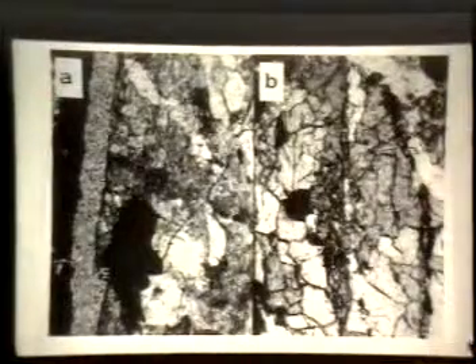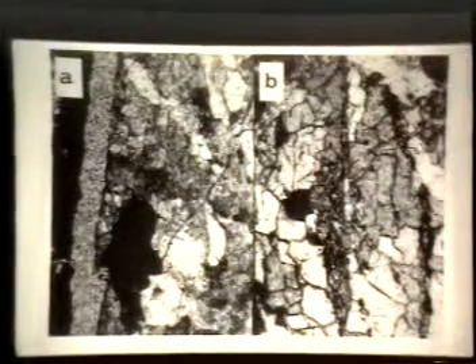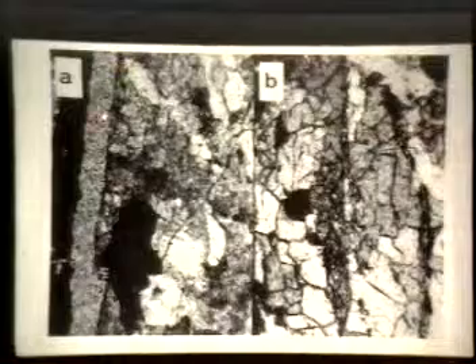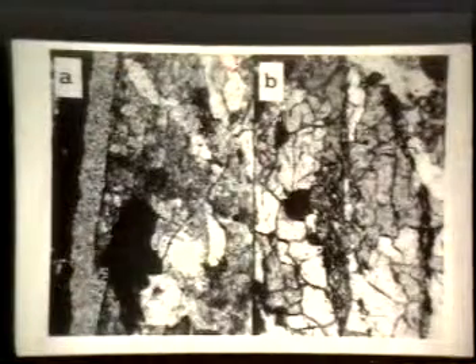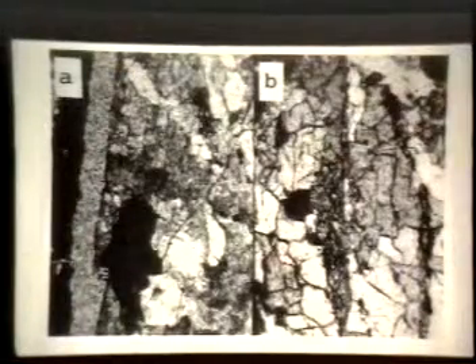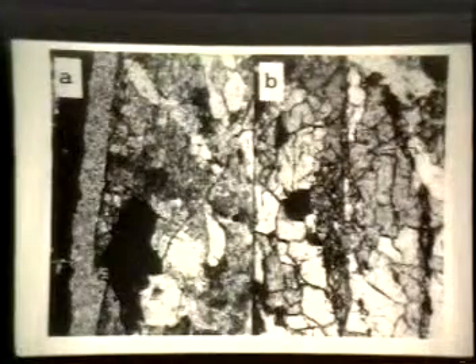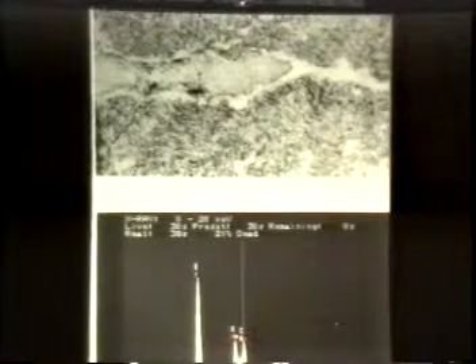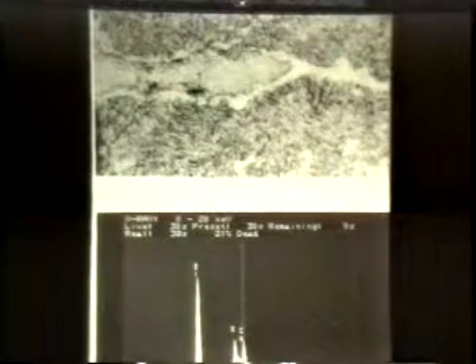This had alkali aggregate reaction, when we examined the concrete, and this is what we found. Reaction rim around the aggregates, polygonal cracking of aggregates. These are telltale signs of alkali aggregate reaction in concrete. And this is the alkali silica gel, which you can see going through the crack. When we identified it, this is the alkali silica gel. This is the composition of the gel. This is what we found in the cracks, filling the cracks.